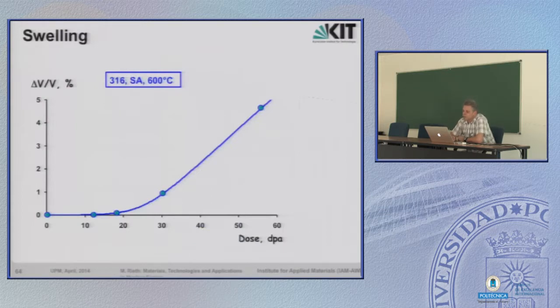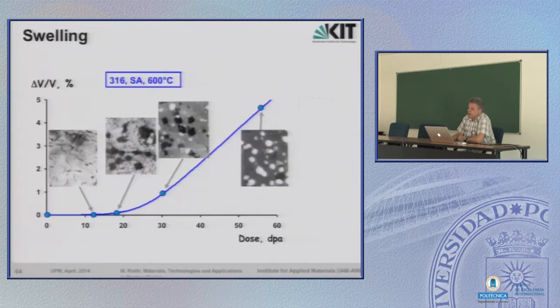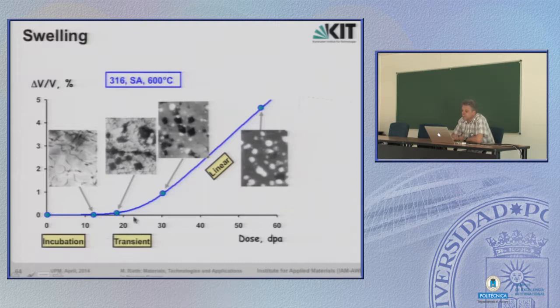Up to now, this is only true for face-centered cubic lattice structure, and this is how swelling evolves with those. Well, forget about the microstructure. For the first few or up to 10 dpa, nothing happens in this 316 austenitic steel. Then some tiny nanovoids are forming, which we call incubation. Then there is a transient evolvement. And finally, you could consider the growth of the voids as a linear dose effect.